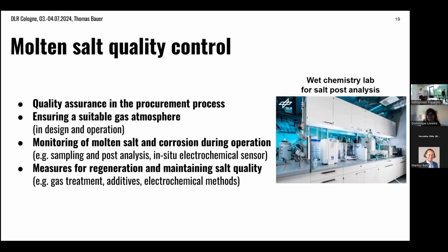Okay, I come now to the topic of molten salt quality control. So trying to go through the whole process. When you use molten salt, first, if the salt is being shipped, you need to do some quality assurance in the procurement process. And then during operation, we need to ensure a suitable gas atmosphere by design, and also in operation to ensure it. We also recommend, and we do it with our plant, to monitor the salt quality during operation and also monitor the corrosion during operation. You can do this by salt sampling and post-analysis of the salt.